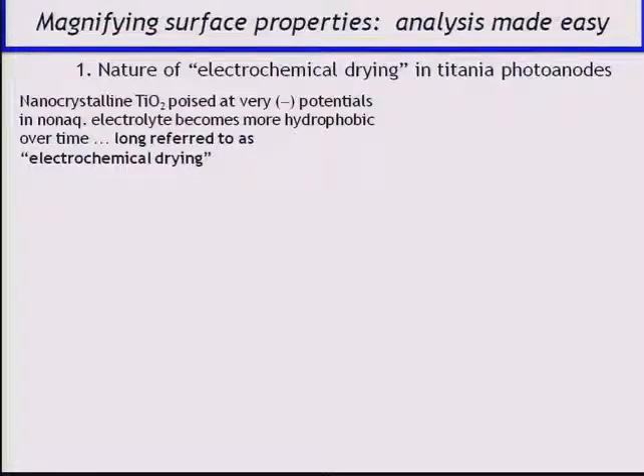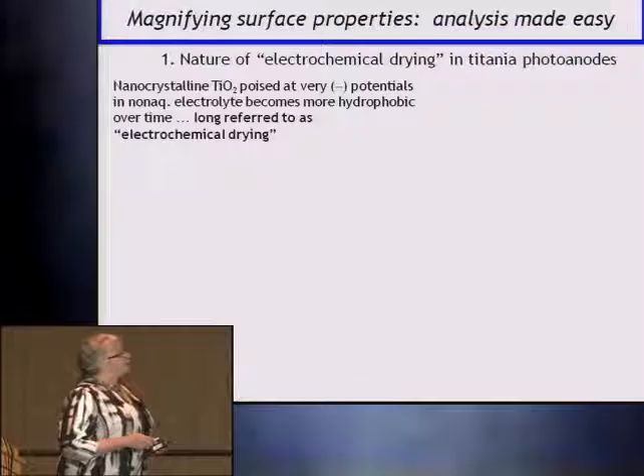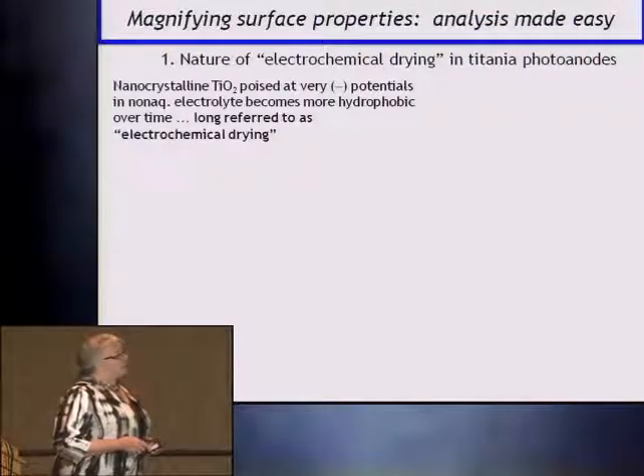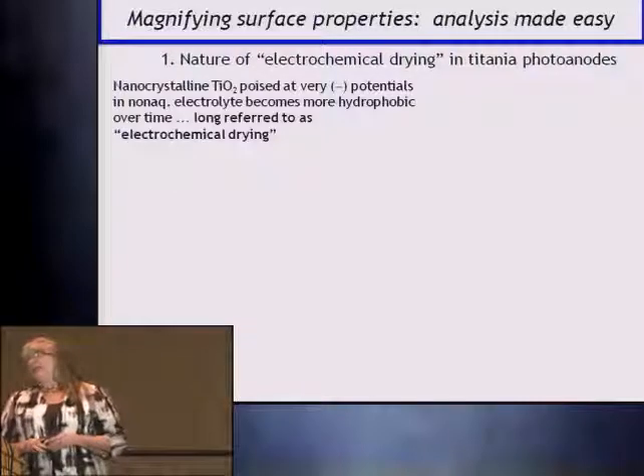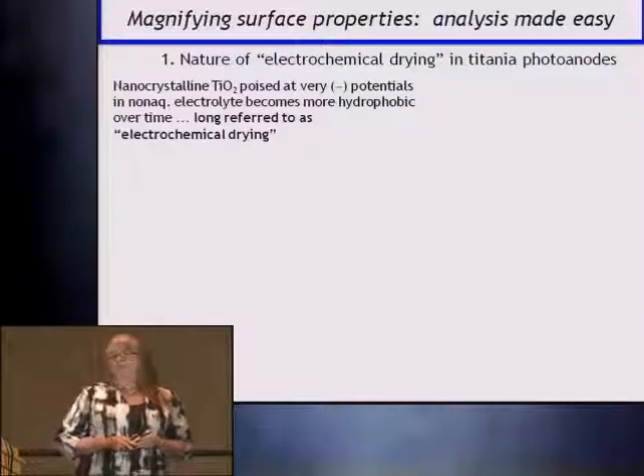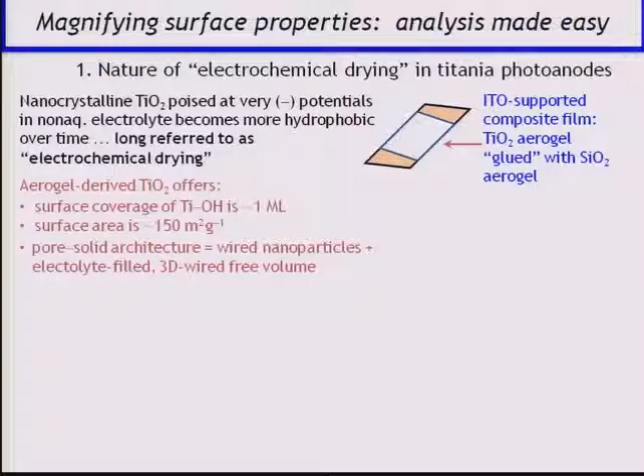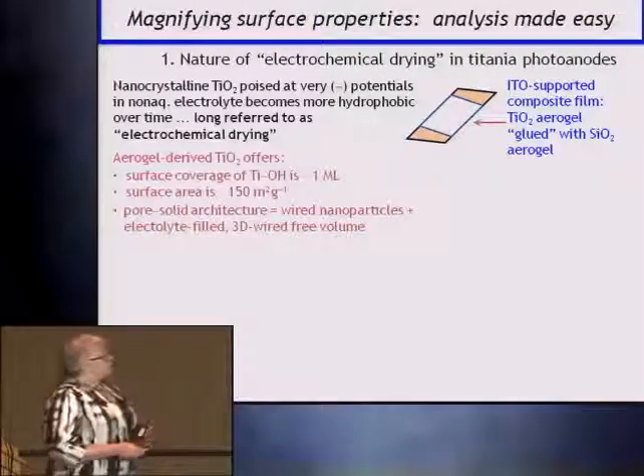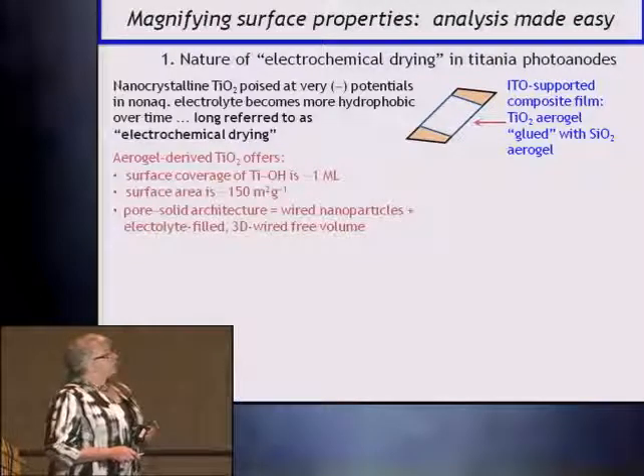So one of the systems we, shall we say, solved just by making it in aerogel form was the quixotic thing known as electrochemical drying. People working with photoanodes of titania, getting the particle size smaller, found that if they could poise these electrodes at very negative potentials in dry non-aqueous electrolyte, it became more hydrophobic with time at potential. That's called electrochemical drying. That helps improve your photoanodic performance. Titania as an aerogel is not very mechanically robust, so we worked with the powder but re-glued it back with silica sol and then dried the composite as an aerogel, heated it to take the titania to anatase. And now you have almost a monolayer surface coverage of titanols. Those are normally defect traps that usually plummet your photoanodic character.